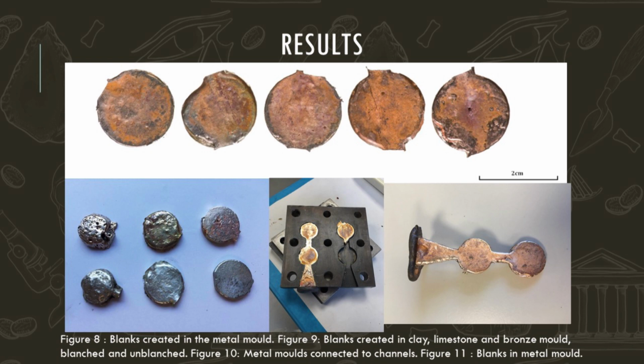And finally, the initial bronze mould castings were unsuccessful. However, upon reflection of the experiments, I did question the effectiveness of using powdered charcoal to coat the mould. The powder just didn't adhere to the surface and it didn't provide the necessary lubrication. So as a result, an additional set of experiments were carried out with just the bronze mould, and this time I used a liquid graphite as a release agent on the bronze mould. And the use of the liquid graphite as a coating agent significantly improved the castings.